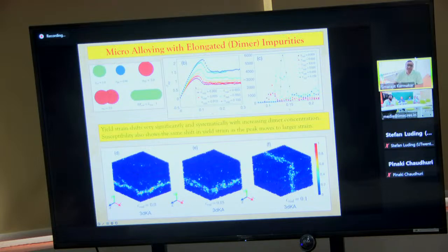when you have zero dimer concentration, then you get the usual stress strain curve, which is represented by these brown symbols in panel B. Then you gradually increase your dimer concentration, and for large enough dimer concentration, which is around 10%, you see that your material becomes much stronger in terms of enhanced shear modulus, and also the peak position moved significantly. So your yielding has been delayed by a very significant amount. So these systems are able to support loads by a large amount.